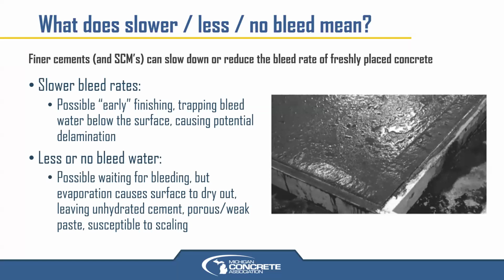If you get on it too early, and densify and harden that surface, a nice smooth warehouse floor or garage floor, pole barn floor, ice rink, whatever, you could trap bleed water below that paste that you're finishing, causing potential delamination. So that could be a concern if the bleed is occurring, it's just occurring slow. What if you don't have any bleed water, or it is just way less than what you thought, and it's never really going to affect the finishing operations? Well, then in that case, maybe you are going to wait for it because you think it's going to come eventually, but you're waiting and waiting and waiting, and it never comes, or it just comes too slow.